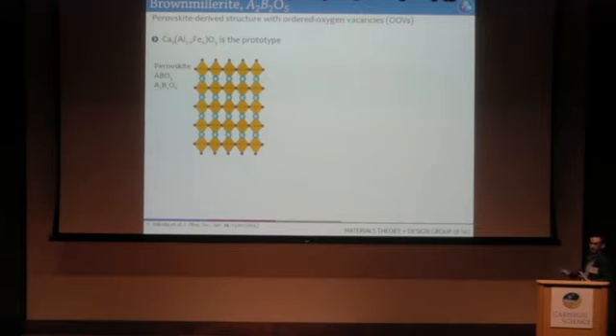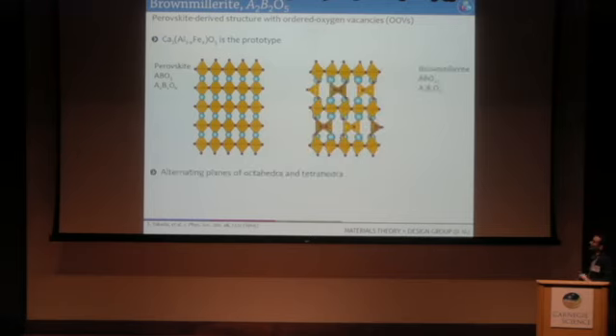This is its chemical composition, A2B2O5. You can start from perovskite. The prototype structure is this aluminum ferrite. You start from perovskite. You take out 1/6 of the anions. And if you do this in an ordered arrangement, you get the structure of brownmillerite. This is alternating planes of octahedra, like this, and tetrahedra, which are linked along this axis. This is the B-axis in the standard setting.